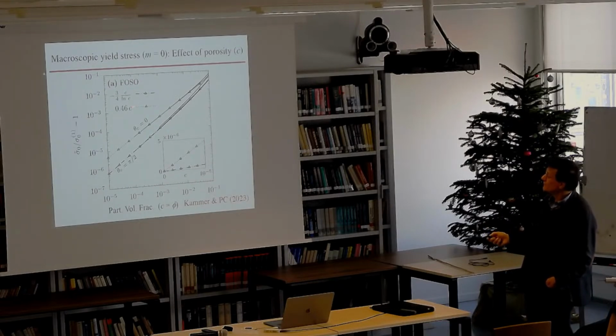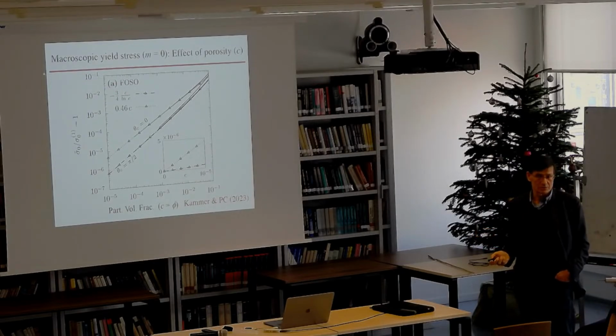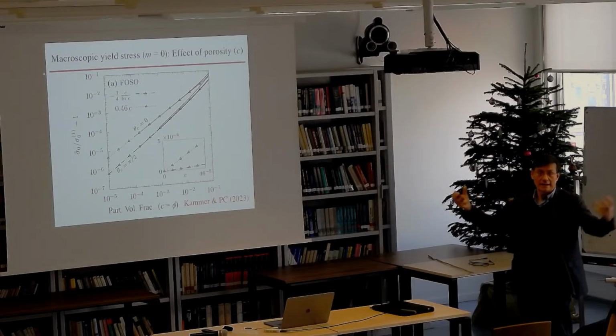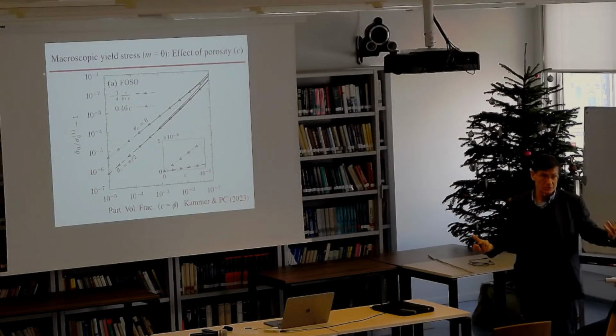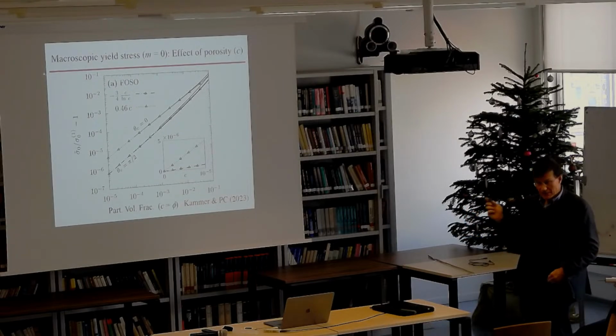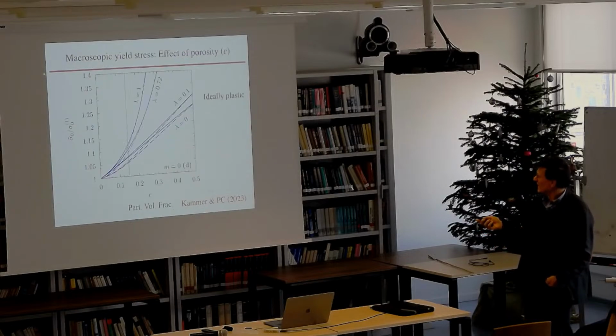This is because of the changing character of the differential equations. You get a behavior that is different: it's volume fraction divided by the log of the volume fraction. The standard assumption that you can just do an isolated particle calculation and then add the result linearly, as Eshelby did for linear elastic composites, fails when you have these shear bands. That's an important lesson that comes out of this.